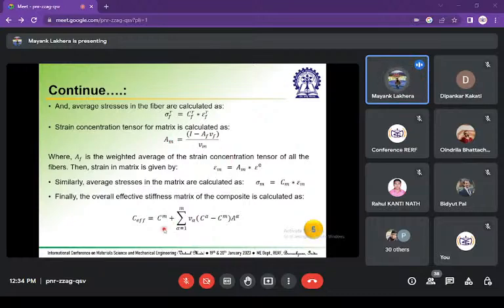Finally, when we have all the formulas, we can calculate the effective stiffness matrix of the overall composite, which is given by this formula. This CM is the stiffness matrix of the matrix material. This V alpha is the volume fraction of that fiber or inclusion. This C alpha is the stiffness matrix of the inclusion. This CM is the stiffness matrix of the matrix. And this A alpha is the strain concentration tensor.